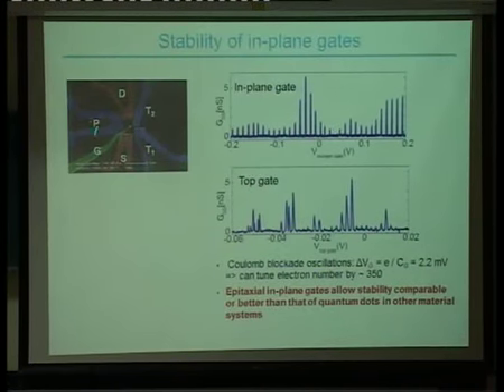But one of the nice things about these phosphorus in silicon devices is that essentially where the phosphorus atoms are, it's very strongly pinned, the Fermi energy. So you can take these devices and remeasure them many, many times, and you essentially get the same result every time. You can warm them up to room temperature, cool them down again. You can even put a gate on top of them once you've already measured them in a dilution fridge. So this was a result with the in-plane gate. We took it out, we put a surface gate on top of a native oxide, so it's not going to be a good gate. And using that top gate, we could go back and we could measure the Coulomb oscillations again. And you can see the key difference here.